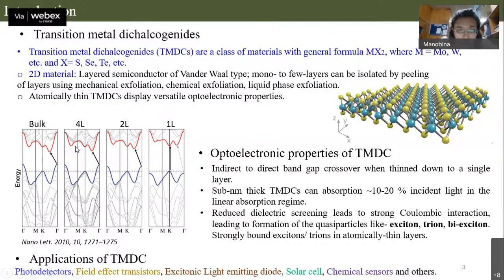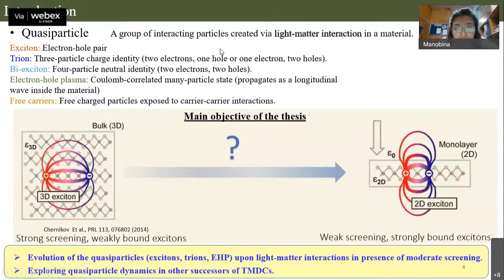These materials have gained a lot of interest due to their different optoelectronic properties. For example, these sub-nanometer thick materials can absorb around 10 to 20% of the incident light in the linear absorption regime. And these semiconductors undergo indirect to direct bandgap transitions while we reduce the layer thickness from bulk to the monolayer limit. Due to reduced dielectric screening in this material, different quasi-particles are observed like excitons, trions, biexcitons. And due to these optical properties, there are various applications like in photodetectors, field effect transistors, LEDs, solar cells, etc. Now, these quasi-particles are a group of interacting particles formed after the light-matter interaction in a semiconducting material.